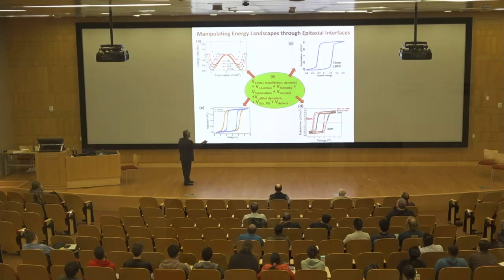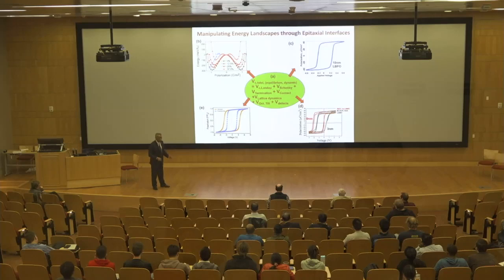This is a 10 nanometer film of lanthanum substituted bismuth ferrite, where the coercive voltage is 200 millivolts. We now know that there are other materials like PZT where you can get very close to the 100 millivolt number. We also know that lattice dynamics plays a big role in the switching properties. And unlike in a ferromagnet, where you don't have to worry about all of this stuff, in a ferroelectric, mechanics plays a big role. Which means if I have a film that's stuck to a substrate, that film will switch differently than when it's released from the substrate. That's what this data is showing.